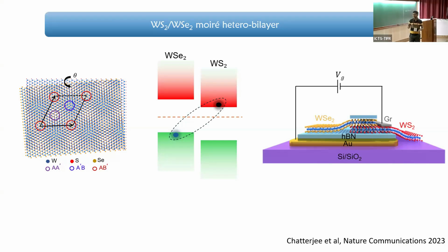There are multiple theories on that. But the bottom line is that this is going to be a much lower oscillator strength exciton, which in some sense is good for experimentalists because it gives you enough time to measure and manipulate them. For example, the radiative lifetime of the intralayer excitons can be on the order of a picosecond, while for this, I'll show you that it can go all the way up to 100 nanoseconds. It's almost like living forever for TMDs.